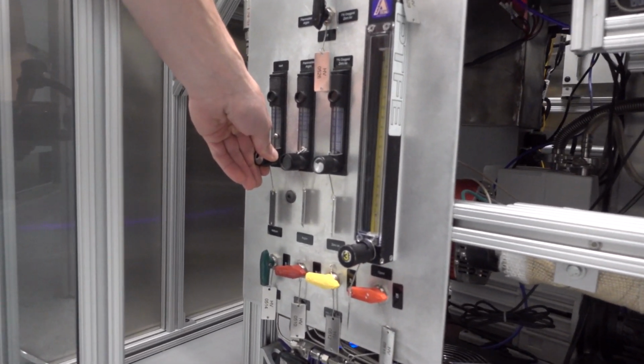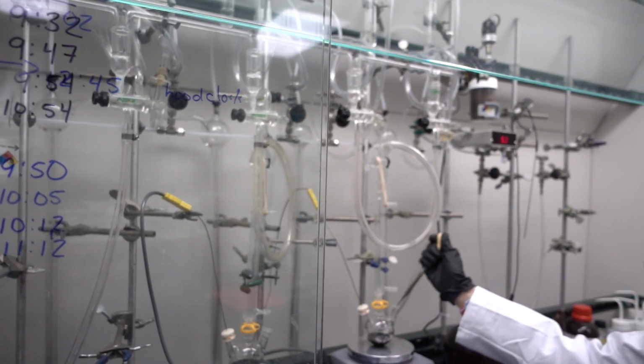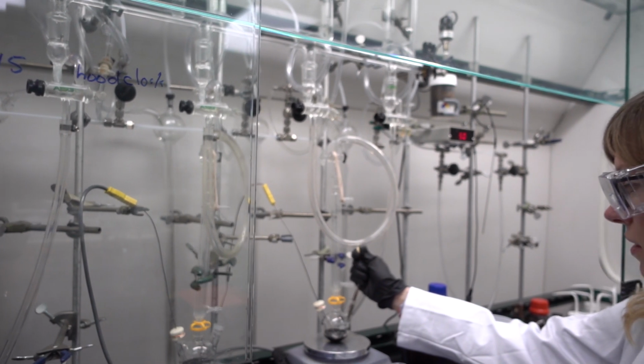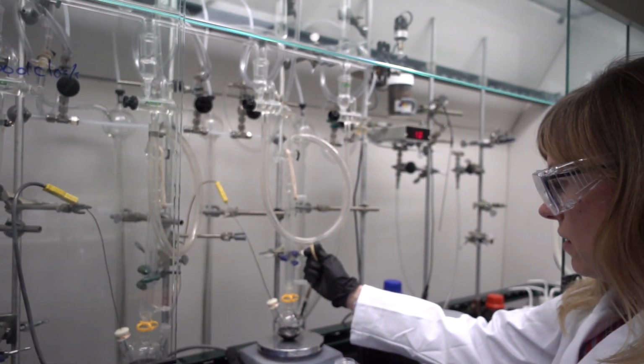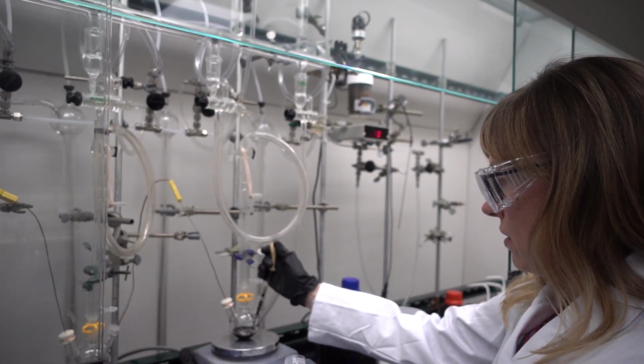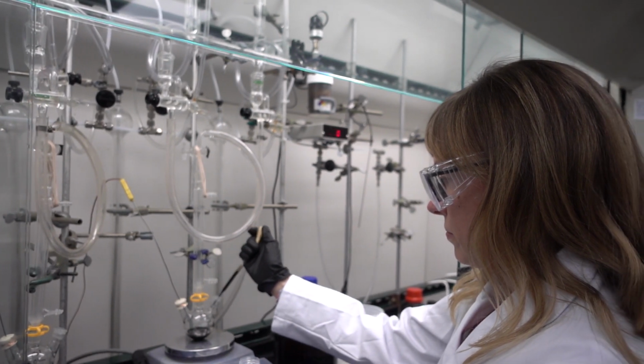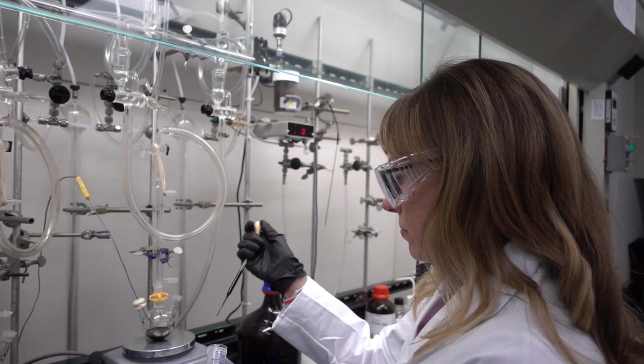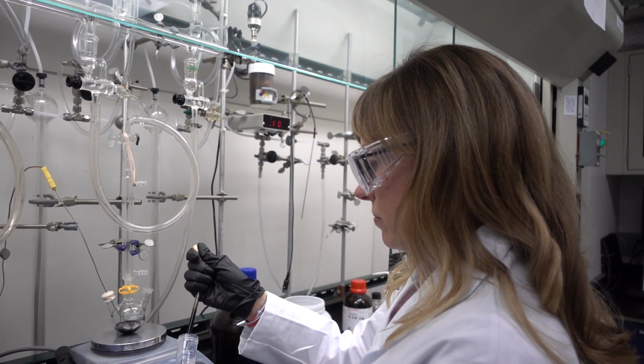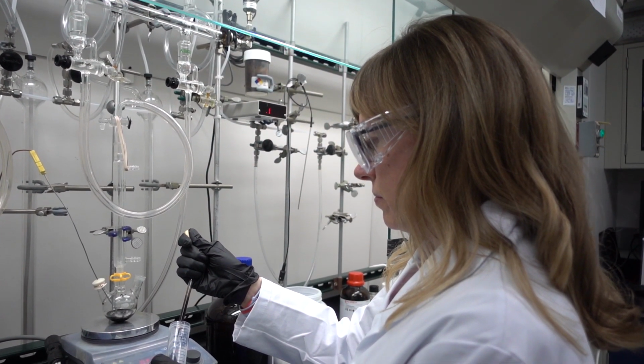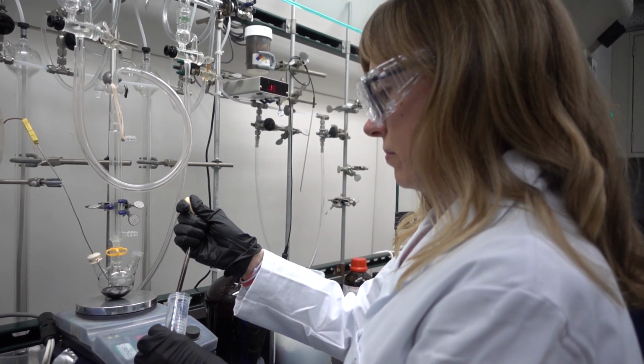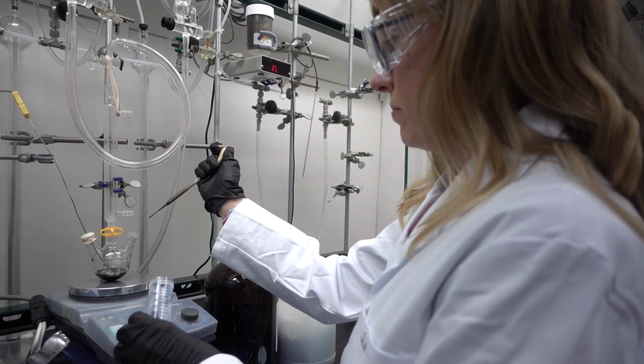Recently, we've been interested in looking at lower severity solution phase synthesis routes to make metal carbides, and these are of interest to us because it affords you a lot of control over the resulting metal carbide structure, and at the same time you can access these metal carbides at significantly lower temperatures, as low as even 250 degrees. We're really excited about some of the solution synthesis routes that are enabling us to make nanoscale metal carbide catalysts.